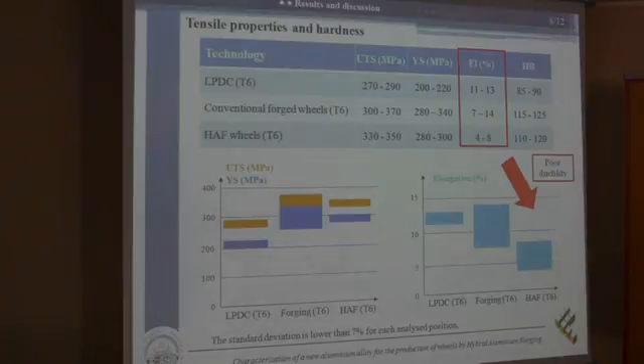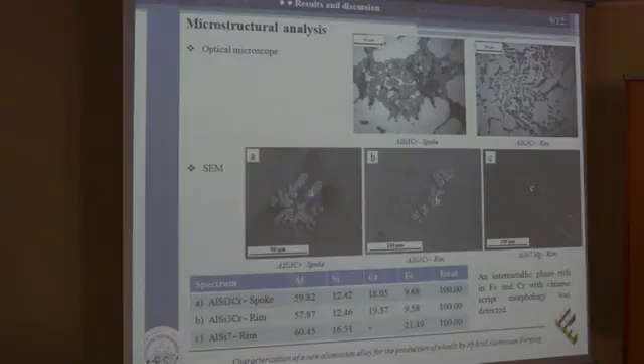In order to understand the reason behind this behavior, we detected by microstructural observation the presence of intermetallic phases containing, as it is possible to see from the table, iron and chromium. These intermetallic phases do not show the typical morphology of iron intermetallics, that is the needle-like morphology typical of cast wheels, but a more complex morphology, a star-like or Chinese script morphology, which is known to be less detrimental for mechanical properties. So this is supposed to have a strengthening effect for the product.